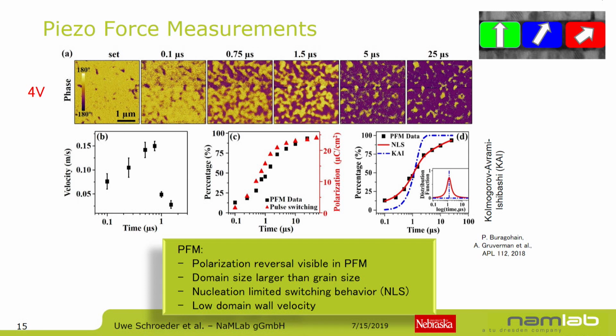Here's some work from Alexei Gruverman's group in Nebraska, and you can see here if you apply a 4-volt pulse to the capacitor structure, you can switch from one to the other polarization direction, and from this you get the domain velocity in the material, and also the nucleation limited switching behavior for these polycrystalline hafnium oxide films. That's all kind of what's expected. You have a thin film with lots of defects, and similar to the PZT case, you expect nucleation limited switching behavior in the material.